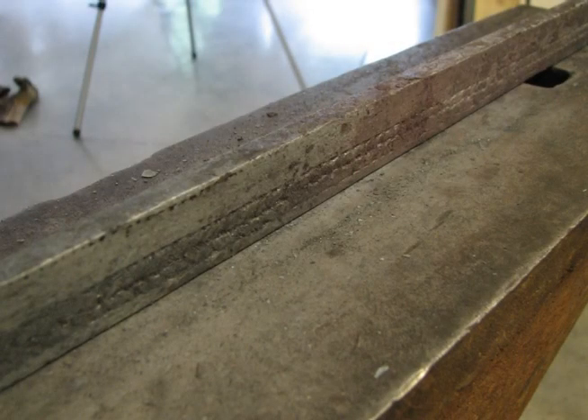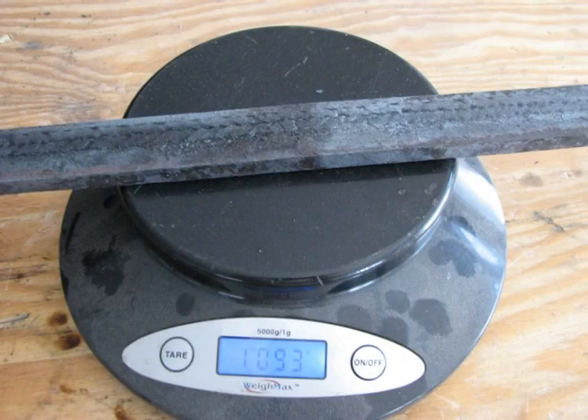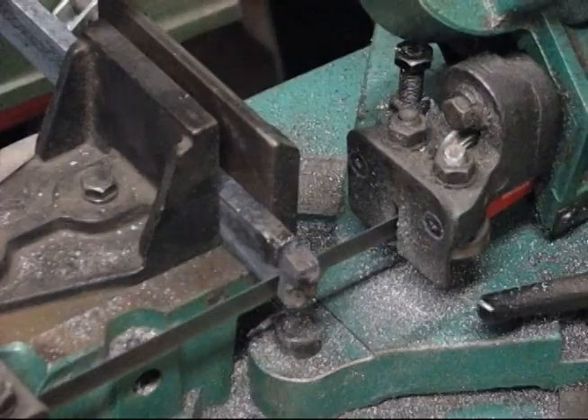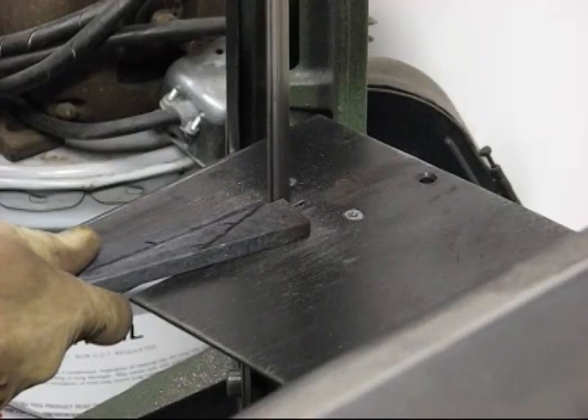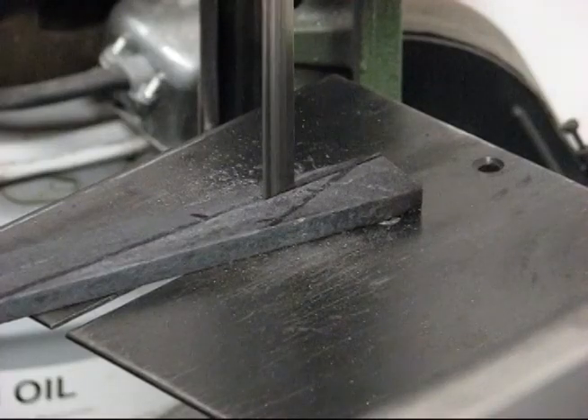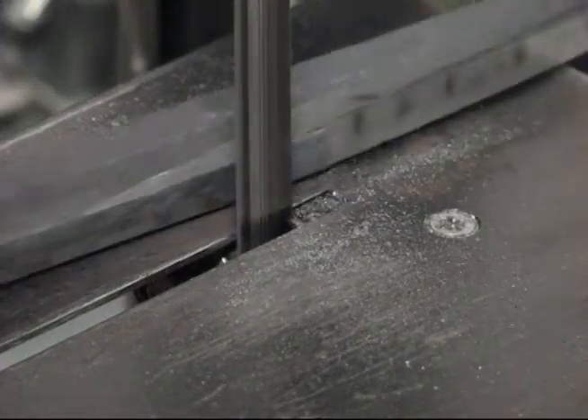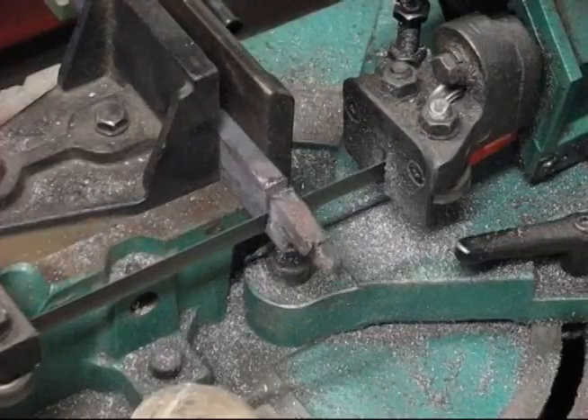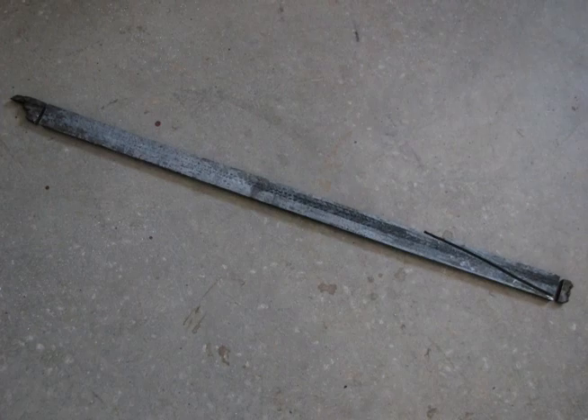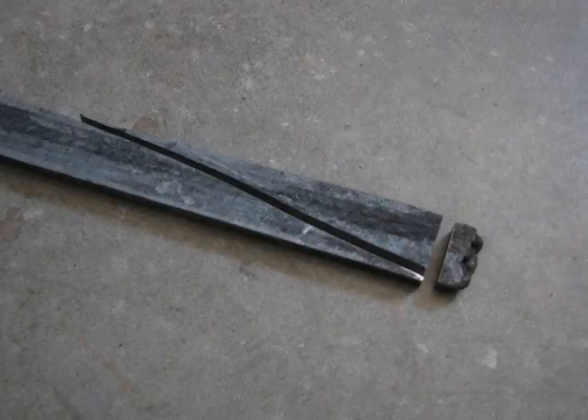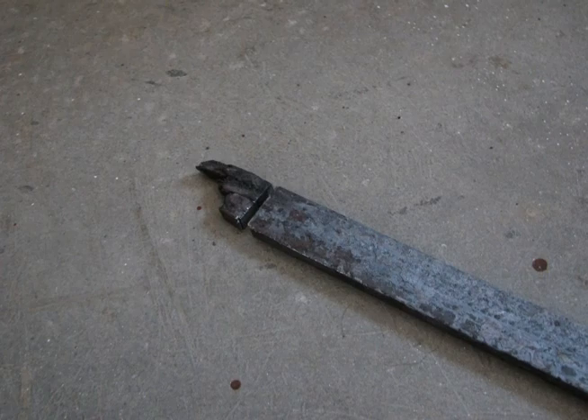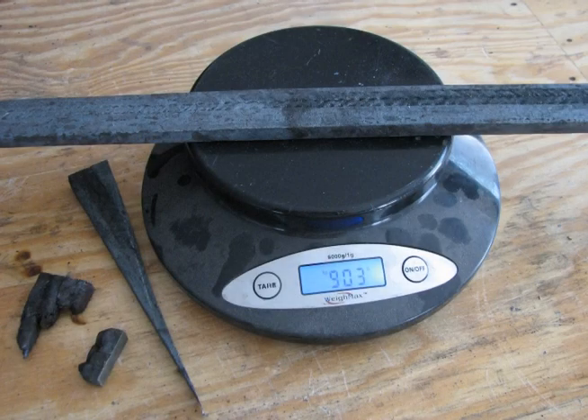The combined weight of the blooms used to make this billet was 3 kilograms, and now we are down to 1/3 of that. The billet needs to be further prepared for forging into a blade by cutting off the rough ends and removing a wedge of metal from the tip of the blade. The tip will be shaped by forging it backwards, causing the twist bars to gently turn upwards, following the curve of the edge. 20% of material has been removed during this operation.